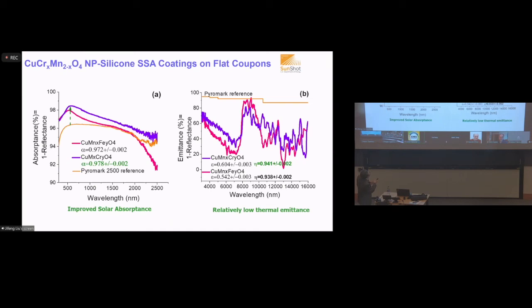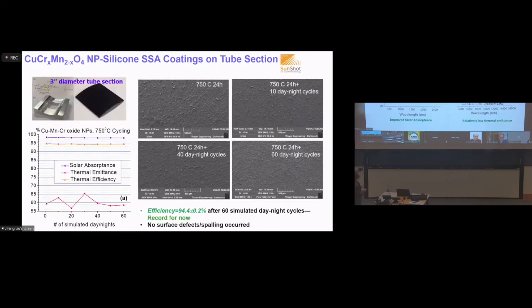The commercial coatings are almost non-solar selective, meaning they basically absorb uniformly all the way into the infrared regime. But in this case, we can actually get solar selectivity over here. This peak is actually due to the silicon oxide matrix itself, and we're considering better matrices to get rid of this peak too.